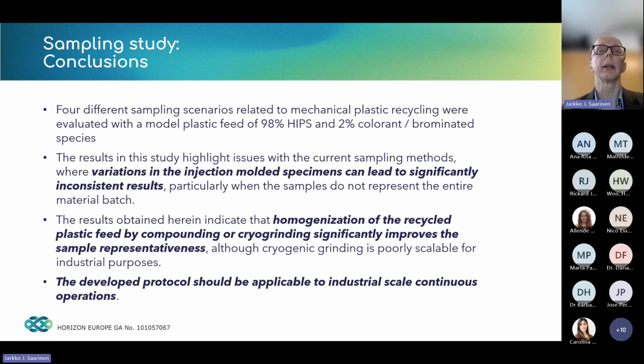However, what we have seen clearly here is that if you do the compounding step, the extrusion step, in between the flakes and the injection molding, we can significantly improve the representativeness of the sampling. In addition, cryogenic grinding is also a sufficient tool for a more representative sample. However, it is suitable for lab scale measurements, but it would not be scalable for industrial scale applications.